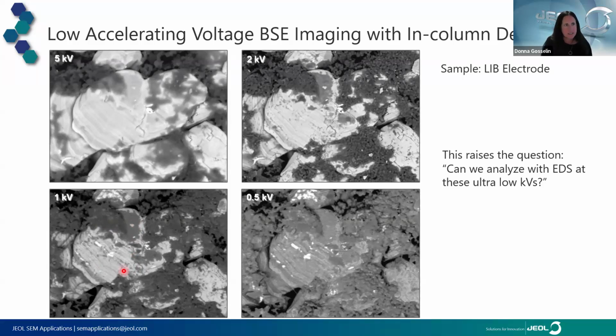It's not really as apparent in the 5 kV image because our electron beam penetration depth is too deep, and we're looking too much subsurface. So by lowering that voltage, we're detecting more of the surface and the materials on the surface of these particles. And so we're getting an idea that we have 2 different compositions here.